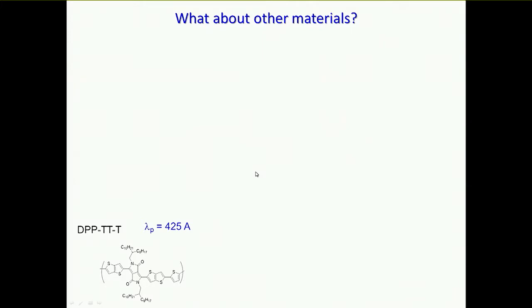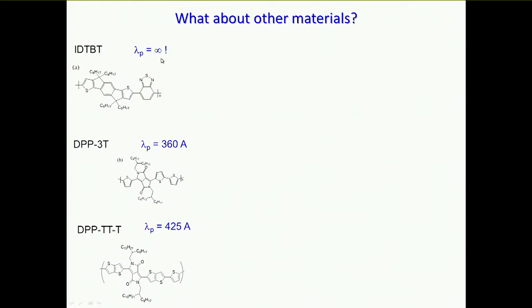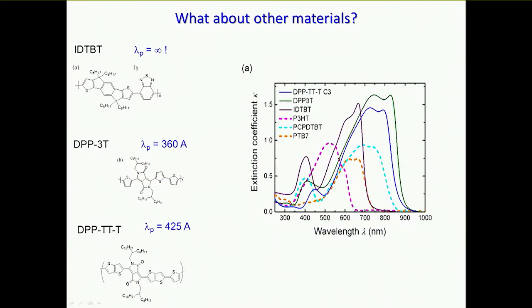So we tried to get this published, and a very, I suppose I'm going to say helpful, reviewer came back and said, okay, why don't you show it for something else? So we thought, okay, let's see if we can show it for something else. And we were quite lucky because we found two something elses. One is actually a close relative of the first polymer; it just has a different configuration of thiophenes in the side group. The other one is one of these IDT-BT polymers, which I mentioned before, are very rigid. We were lucky enough to have samples of different molecular weight of at least the IDT-BT. Then we went off and measured them, and I can say we were absolutely delighted to find that both of these polymers, which ought also to have a high persistence length, also displayed a strong optical absorption, and so that at least supports the idea.